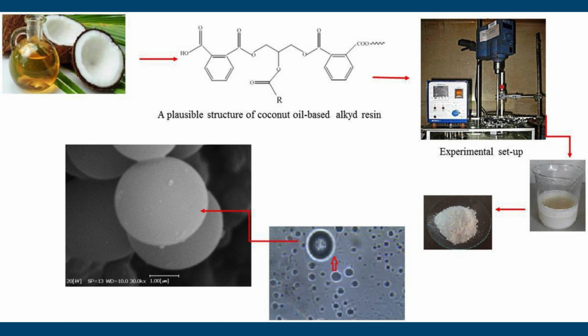To facilitate the removal of water generated during esterification, a small amount of xylene is added, enabling azeotropic distillation. The reaction is continued until the acid value decreases to approximately 5 mg potassium hydroxide per gram of resin, indicating near complete esterification. The final product is diluted with xylene to obtain a solution of about 60% solids, with a viscosity of approximately 10.7 Stokes at 25 degrees Celsius. The resulting resin typically contains around 15% fatty acid content and exhibits an average functionality of approximately 2.6.